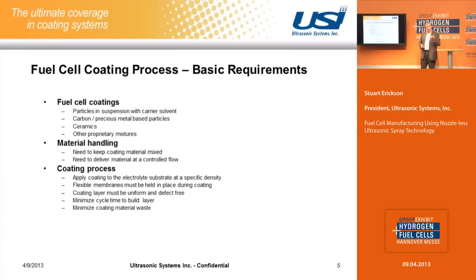What we're doing is we're applying this anode and cathode layer at a specific density to the substrate. And we can either apply it to a flexible membrane or to a metal type or ceramic plate. When we're dealing with a flexible type substrate, the substrate has to be fixtured and handled such that it remains flat during the coating process. We essentially need to apply a coating that is uniform and defect-free, and I'll go into more details about that later. And we also need to minimize coating material waste.